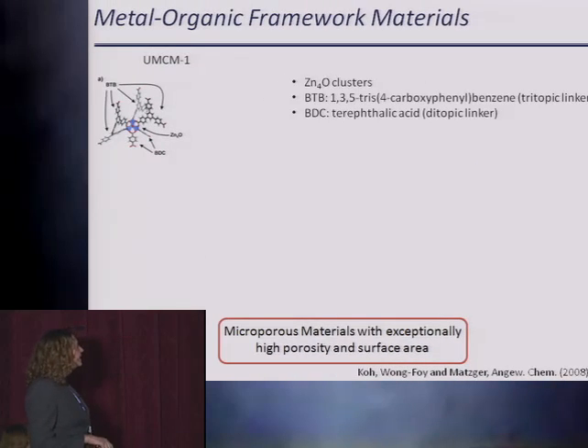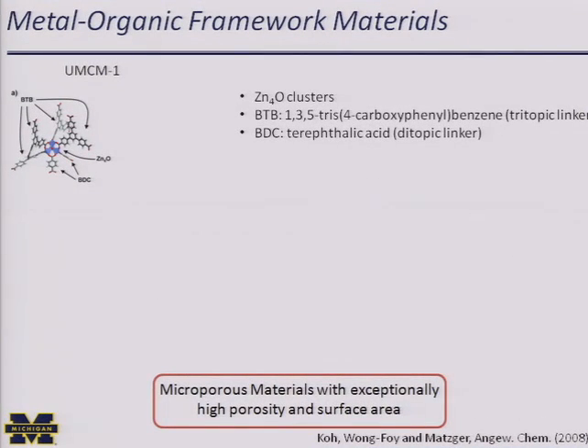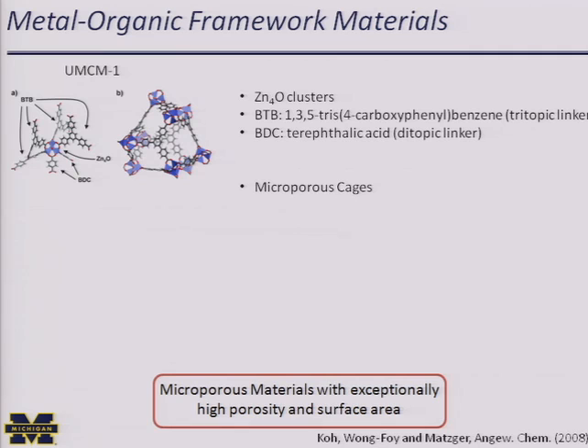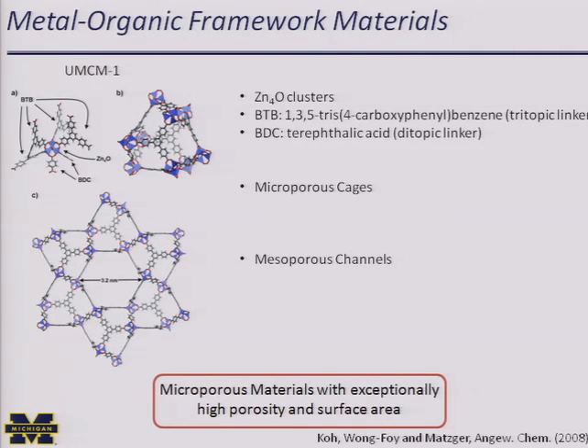What we've been doing is looking at metal organic framework materials, so switching completely to the solid state. And this project is a collaboration with my colleague Adam Matzger, who's also in the chemistry department. So, for example, if we look at these materials, UMCM1, which is University of Michigan crystalline material 1, these are made up of metal centers. So here's a zinc cluster at the center and different types of organic linkers. Here we have the tritopic BTB linker and the ditopic BDC linker. So units like that come together to form microporous cages and finally mesoporous channels in the whole crystal structure.